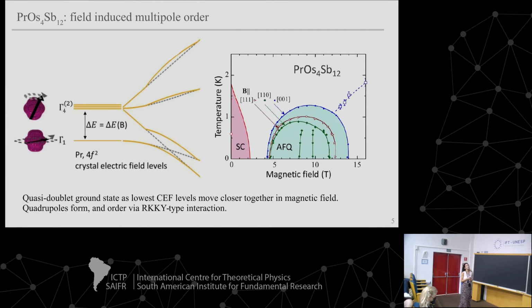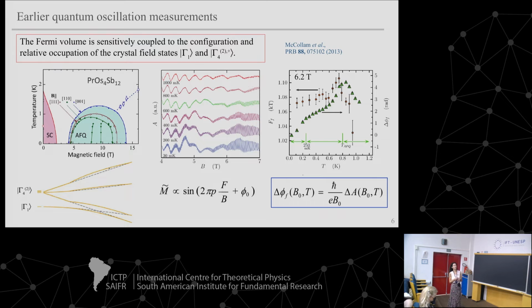Okay, so why do we want to measure to low temperature? This phase diagram was mapped out already quite some time ago, but we were looking at quantum oscillations and the Fermi surface to see if we could understand a little bit if there's some quantum criticality or some effects of quantum criticality associated here, and also if there was any change in the Fermi surface across this level crossing.